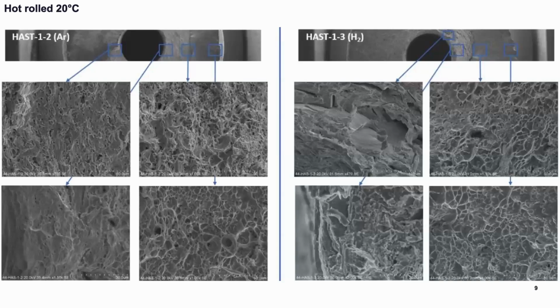If we have a look at the fracture surfaces, it is mostly ductile fracture. For the specimen tested in hydrogen, we can see some localized small areas of more brittle fracture, but overall quite ductile. These areas are located close to the hole where we have the hydrogen exposure. We also observe, though it can't be seen here, that secondary cracking inside the hole is more pronounced when we test in hydrogen compared to argon.